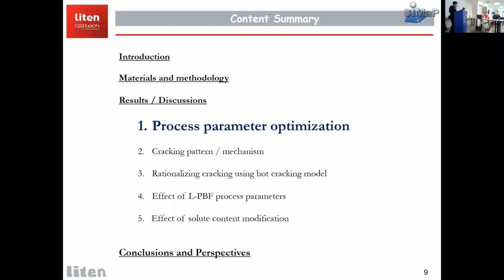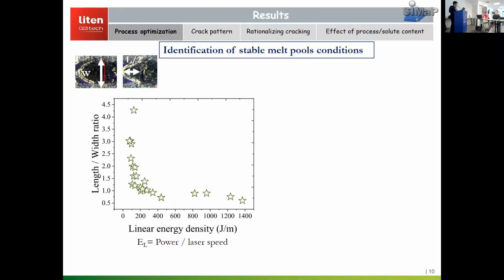So, moving into the results and discussion of this process optimization methodology. To start with, we did some basic single track analysis, and we studied the melt pool dimensions, for example, the length to width ratio as a function of linear energy density. Linear energy density is nothing but the ratio of laser power to laser speed. So we can see clearly a rectangular hyperbola. For example, if you are at low energy, you have a high length to width ratio. And if you are at high linear energy density, your length to width ratio decreases.